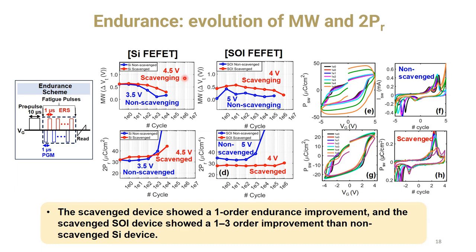That is pretty understandable because the scavenging device has a thinner IL. A thinner IL represents less chance of getting trapped inside the silicon oxide. So a thinner IL can cause better endurance. However, this SOI FET has better endurance compared to the silicon FET. It is still unclear why the endurance is better than the silicon FEFET. More research is required.